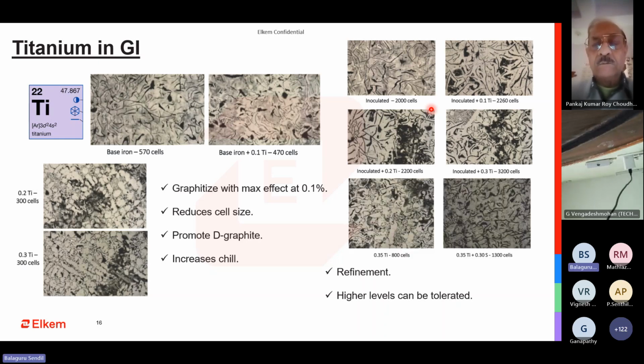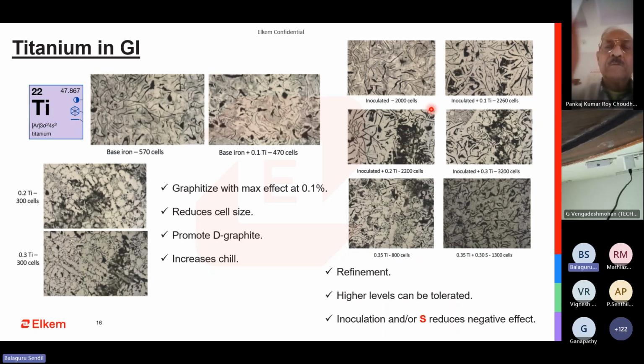How do I neutralize titanium with respect to gray iron? I can also increase the sulfur in my charge mix, in my base metal, to neutralize the negative impact of titanium. That is, the D-graphite formation can be nullified with good inoculant, as well as having a bit more sulfur in your base metal. So this is again subject to the foundry conditions, to the grade that they are making, to the type of casting, to the type of layout of molds that they have, their pattern methoding and everything.